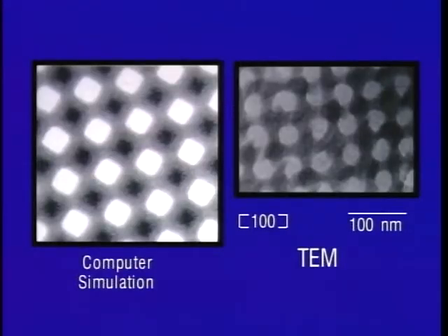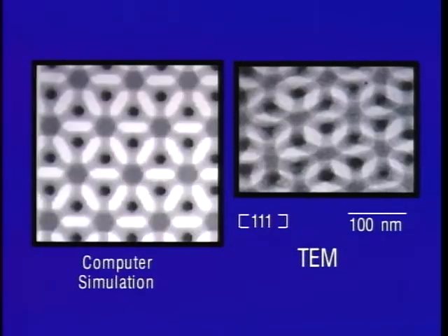And here we see a series of them showing a pretty good match between the experiment and the simulation at angles that are previously determined to illustrate both the cubic structure of this particular triply periodic surface from one point of view and a diamond structure from another.